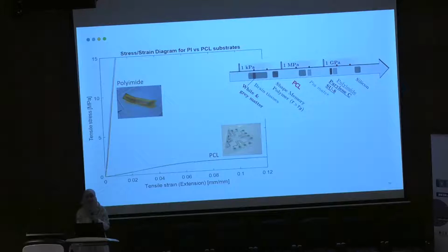It also has a Young's modulus that is considerably low. It is pretty close to the neural tissue. Here we have the brain tissue, which is in 1 kilopascal, and PCL is in the range of megapascal. Also, we compare it with polyimide, which is a common polymer that is used in prosthetic devices. So PCL shows a very small Young's modulus compared to the commonly used polymers, and this enhances the mechanical match with the neural tissue and will reduce the inflammatory response.